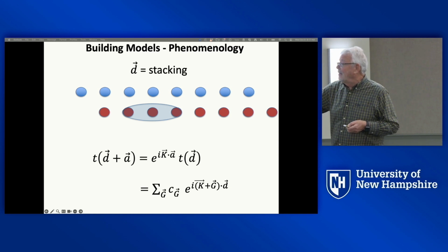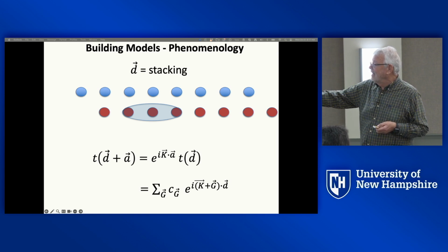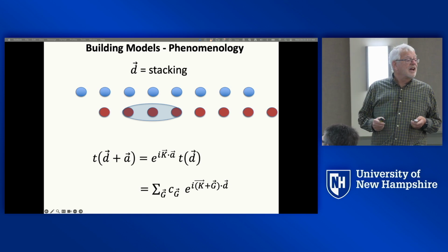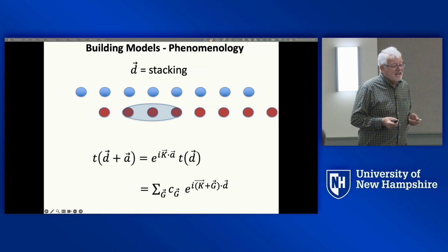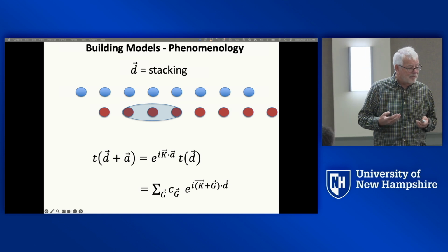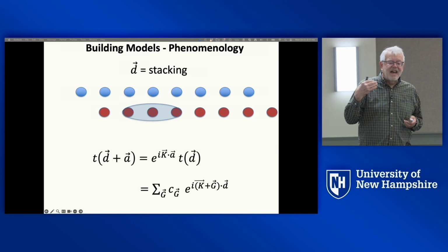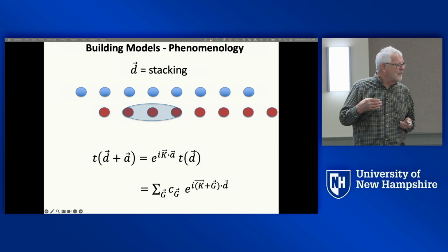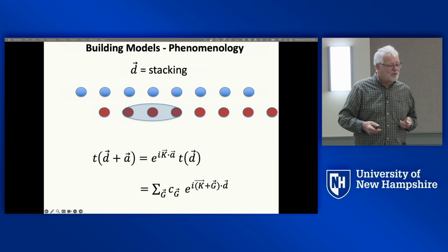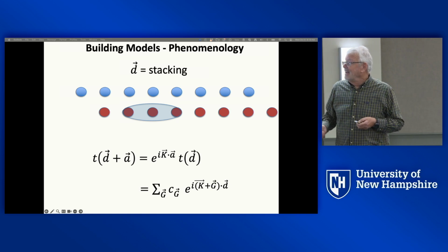And so here's one way of making a model of a Moiré system. Let's say I have two weakly coupled layers, and I know that the dominant physical process by which the layers interact with each other is that electrons can tunnel from layer to layer. That's the case, for example, for carbon, because carbon atoms are neutral. They don't make an electric potential in the other layer.